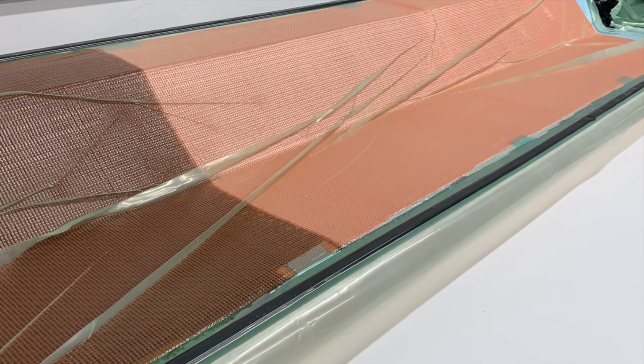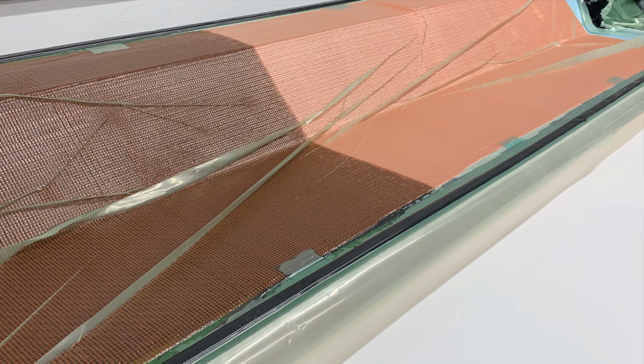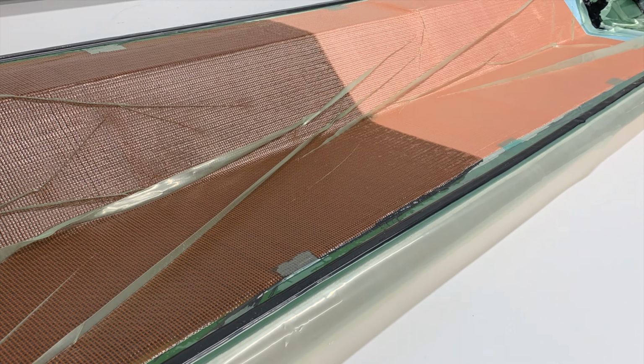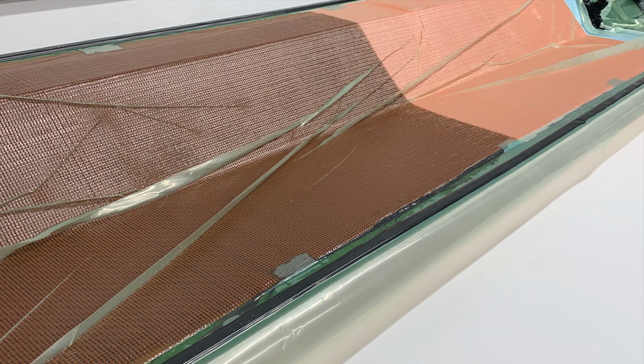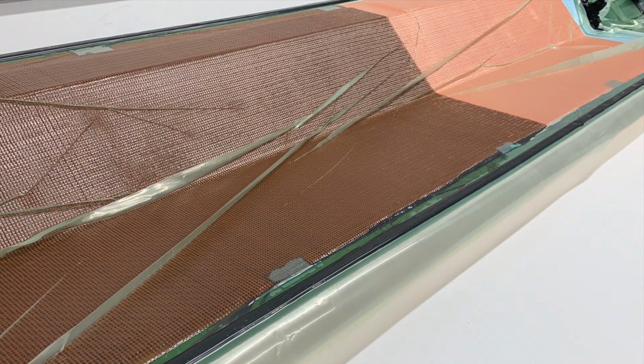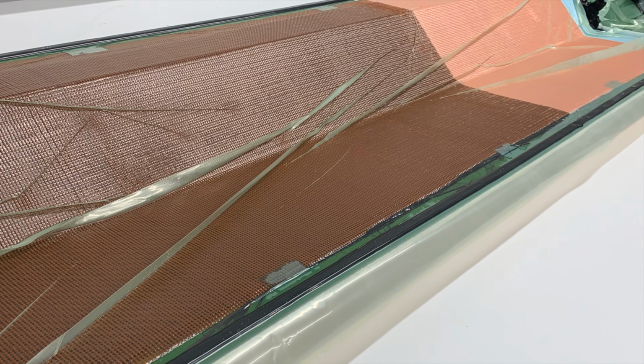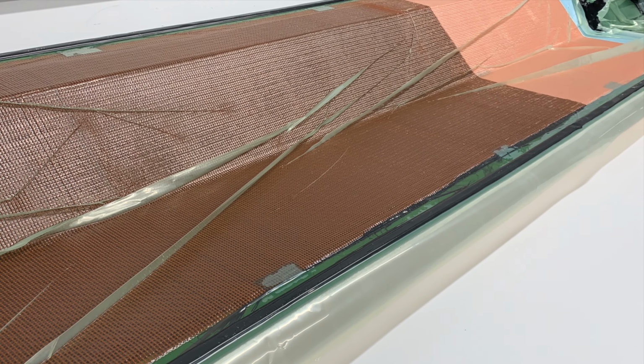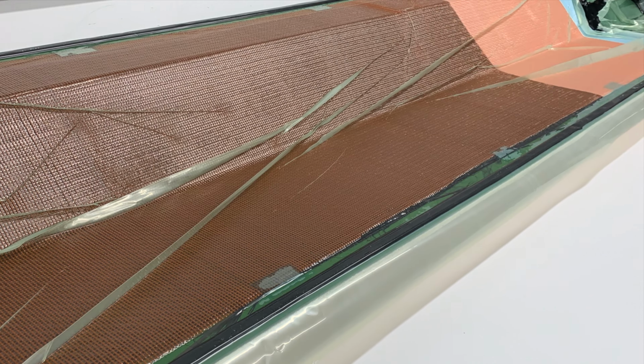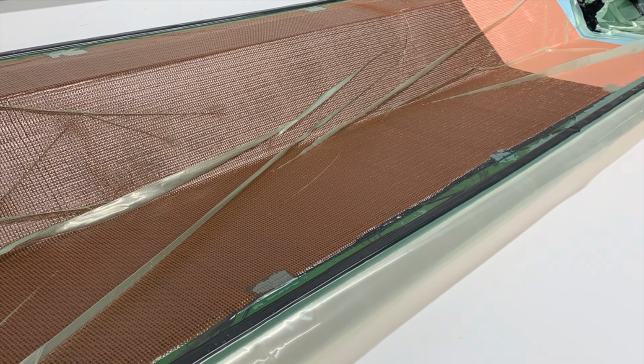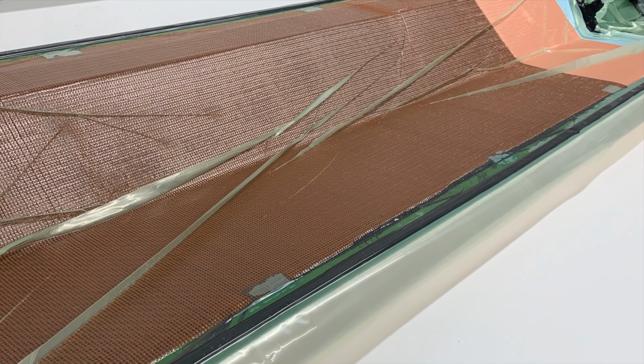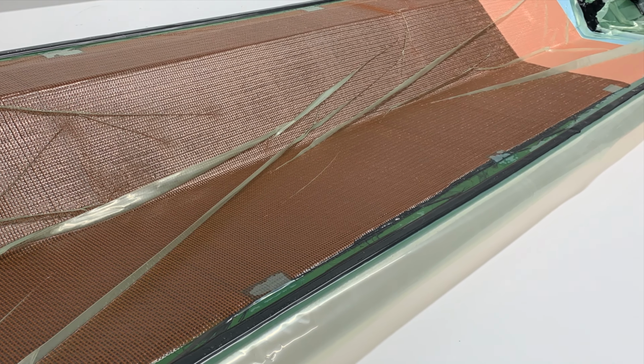It took us around 41 minutes to complete our infusion, well within the pot life of our IN24 resin. It would also be possible to infuse up the mould surface instead of across, but it all depends on your infusion strategy, shape and size of your part. If you have any concern about your resin exotherming before entering the vacuum bag, then consider our slow hardener and potentially mixing and adding your resin in batches to the resin in pot.